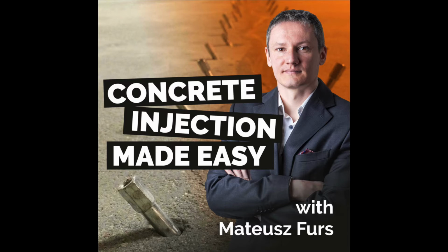Sure. Okay. So when I inject cracks in the bottom slab, somewhere between 50 centimeters and even up to 1 meter thickness of concrete, and there is a crack, I love to use acrylic gel for this kind of application. And we use this acrylic gel where the part B is mainly water, because this material has a very low viscosity of around 7 millipascal seconds. Do you find this material a good solution for cracks in concrete?